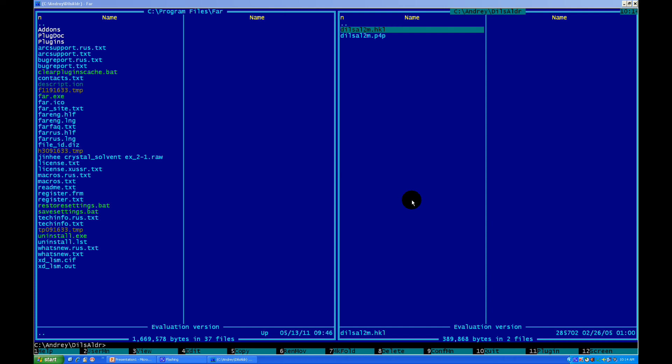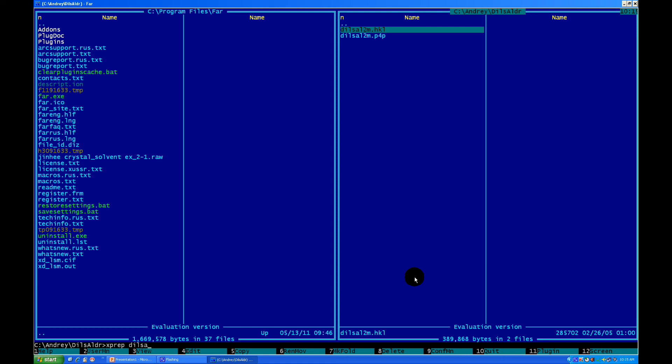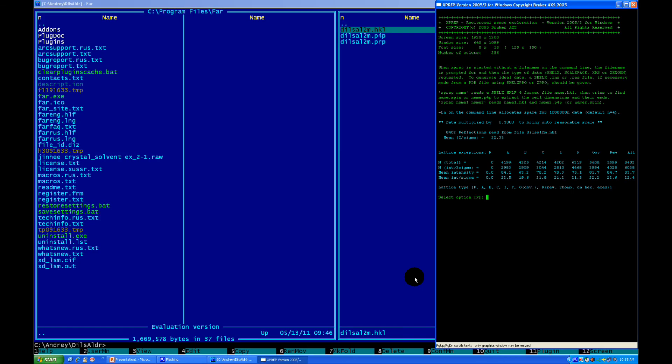To start working, what you need to do is, in here, in down bottom, first thing what we're gonna do is to find the space group of the unit cell, and we will prepare files for structure solution. We're going to do it with a program which is called xprep, or x-ray preparation. To start it, what you need to do is to type xprep, and then you need to type the name of file without extension. In my case, it would be dlsa2m, and press enter. And that starts the xprep.